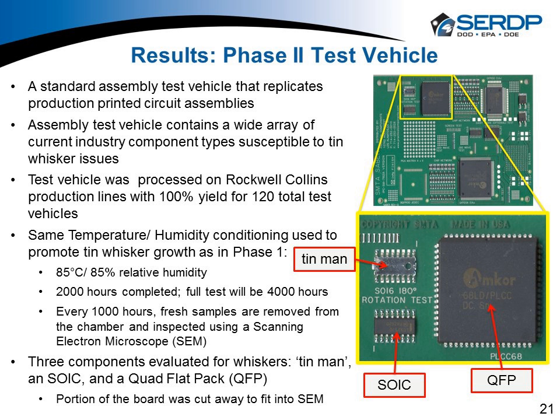And the one thing that was really nice is if you look down here in the lower image, there was an SOIC with a standard component, but on this test board, there are two positions for this SOIC. So we actually took our Tinman, tape and reeled them, and so when we put this one down, we didn't put its twin sister. We put the Tinman in place of what would have been a plastic component there. So on our card, what we took to our SEM for analysis in phase two, we were able to look at Tinman again. We were able to look at a commercial SOIC, and then we were able to look at a commercial QFP.